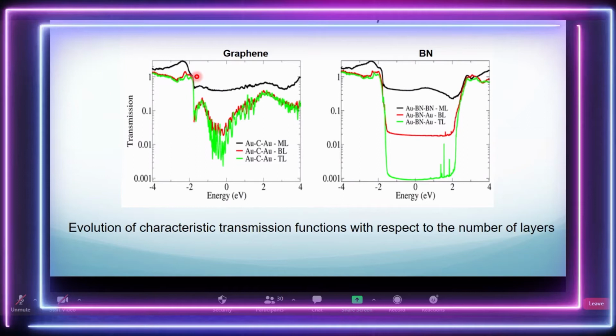So we thought, okay, instead of varying the distance, let's increase the thickness of the 2D material and see if it matters. What you're looking at here is graphene. We have monolayer, bilayer, and trilayer. So in a sense, by increasing the thickness, you are weakening the effect of the interface. And that again shows up here: for a monolayer, there's a very large transmission function. You go to the bilayer case, which is in red, it reduces. And for the trilayer, it also goes down, but it remains finite, which is fine, because graphene should have a transmission function near the Fermi level because it is a zero gap material.